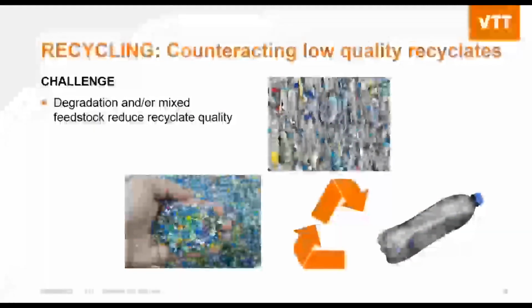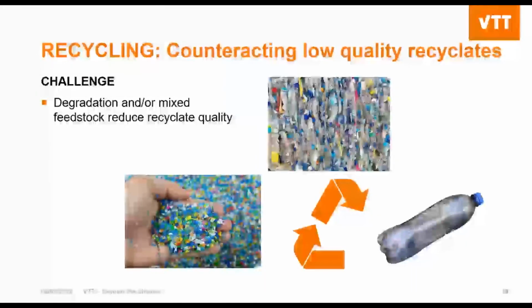Then if we continue with another major concern, as we know, the plastics, we have a wide range of different applications, a wide range of different polymers, and even a wider range of different additives that are used with the polymers to form the plastics. One very big challenge is the heterogeneous, varying quality of feedstock. So especially for the mechanical recycling, the effect of inefficient sorting and polymer degradation during reprocessing is something that is of concern. And this leads to both low quality recyclates and eventually breaking the circularity loop. And this is something that we have also thought about how we could overcome.